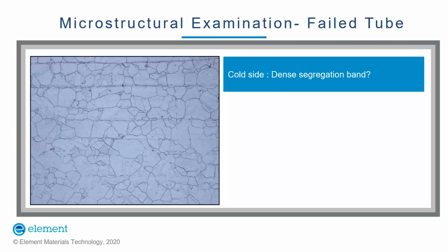Microstructure at the cold side showed segregation bands of precipitate, as you can see in the micrograph. As per the supplied information, cold side temperature is supposed to be below 100 degrees centigrade. Therefore, it can be confirmed that this segregation band formed during the manufacturing process of the tube.